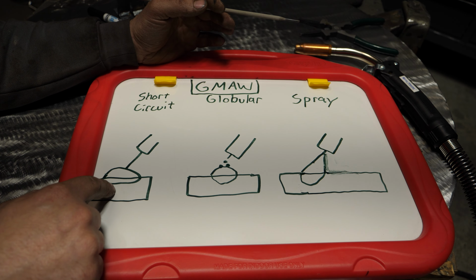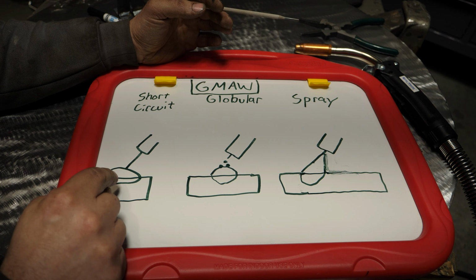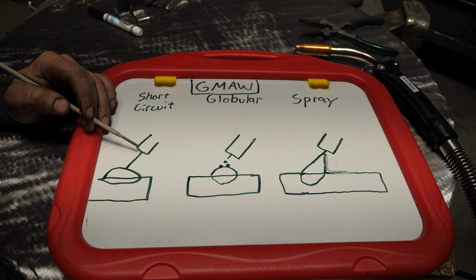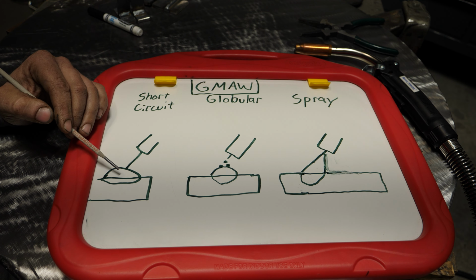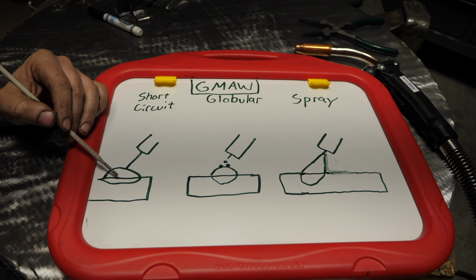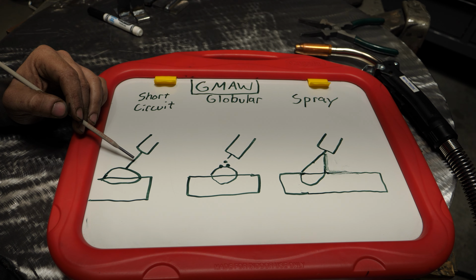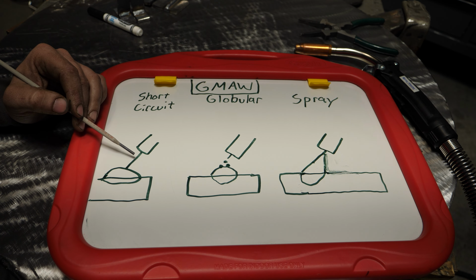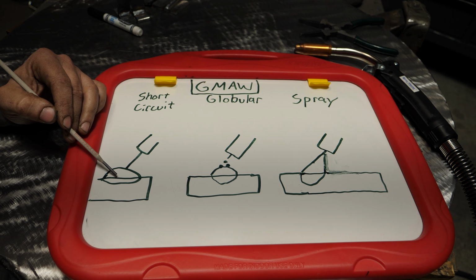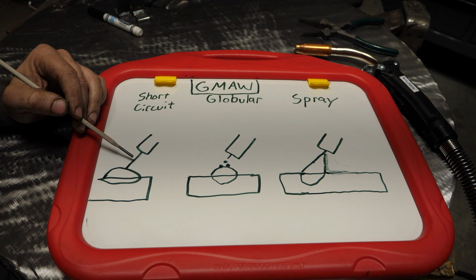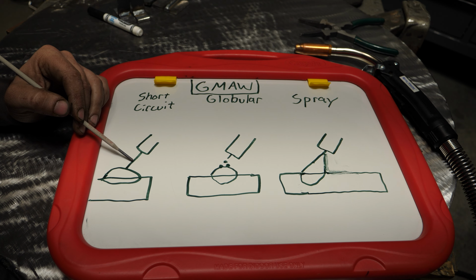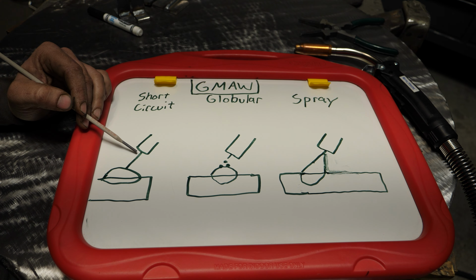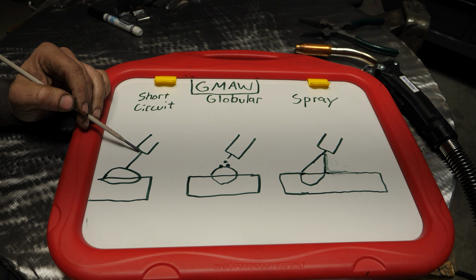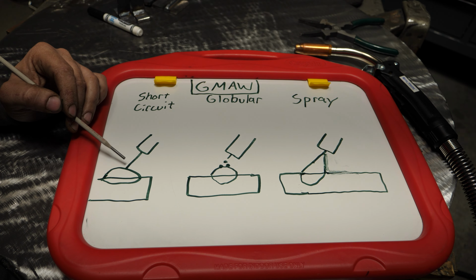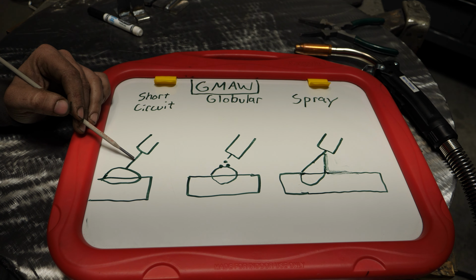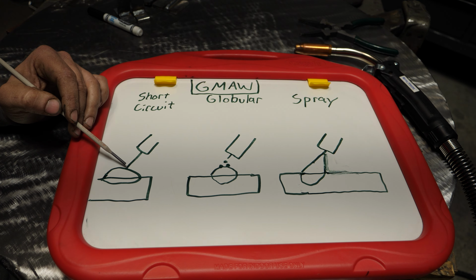Short circuit has a lot of, how do I say, limitations to how it works. Basically, the wire gets fed out of your contact tip. It stabs the molten puddle in the plate, and then it shorts out, blows up because the current's so high the wire can't handle it. And then the wire gets pushed out again and does the same thing over and over many, many, many times per second. And that's what gives short circuit its crackle. At no point is that wire essentially liquid when it's moving from the contact tip to the molten pool. It's one solid wire and it only blows apart.